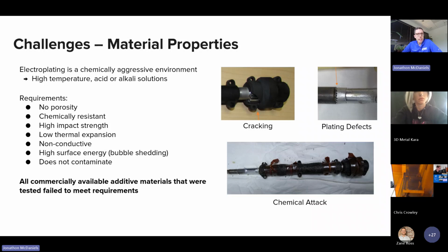The requirements we set out to meet at the beginning: you need to have no porosity. If you have porosity, it's going to soak the toxic plating solution up, and it's going to leach it out. When you're done with the process and you set the mask on a shelf to be used next time, you're going to come back and it's going to have leaked out a bunch of hexavalent chrome all over the place. The mask needs to be chemically resistant, needs to have high impact strength,